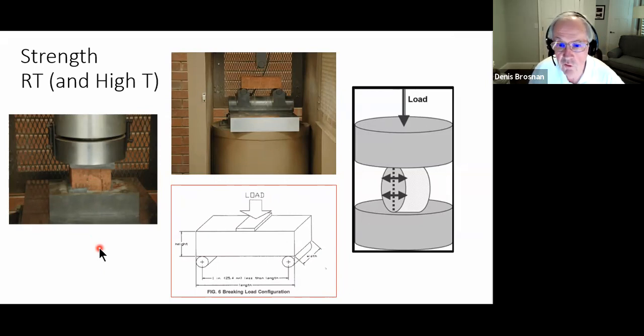But we also want to measure tensile strength in ceramics, and that's hard to do. So the center picture is a 3-point bending test. The ceramic, in this case a brick, is supported on 2 points, and an upper ram comes down and contacts the ceramic, and pressure is applied to break the ceramic. That's just like this diagram right here, which is a little easier to see. The load is applied in the middle and the support is on the ends. And by calculation, we're able to determine the maximum strength at failure in the surface of the ceramic.